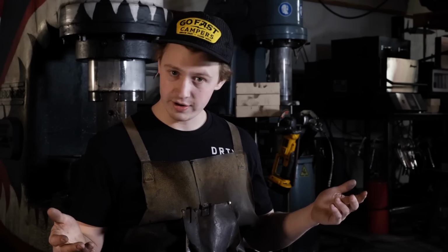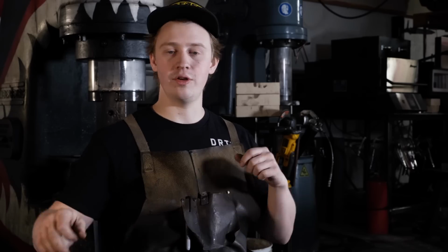Or if you cut it into 4-inch long pieces, you can take that 25 layers and stack it up 6 times. Congratulations, you're at 150 layers. Good for you. Yes, I did it. Pretty cool, huh? Now, the downside of letting a billet cool down and grinding off all that material is that you're going to lose a little bit of material on your ends, and the material you lose to grinding, so you're going to lose a little bit more material than you do with the hot folding method. But you have a higher chance of success, and you have the ability to exponentially multiply your layers faster. I and most professional bladesmiths prefer the cool down and restack method, and we'll get into a little bit of pattern development later on, which is another reason why that method is pretty handy.